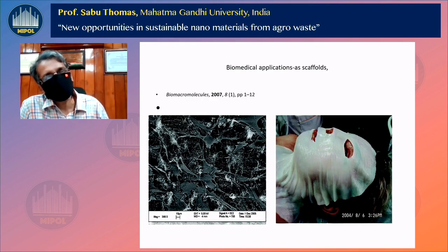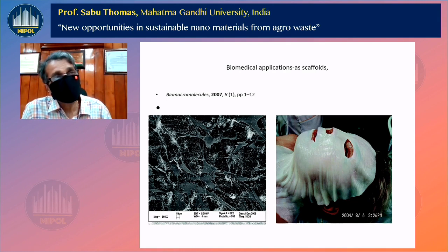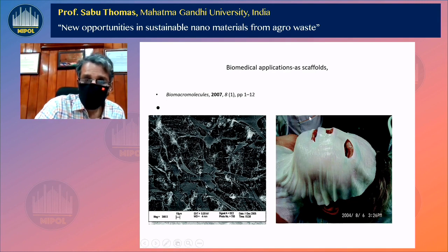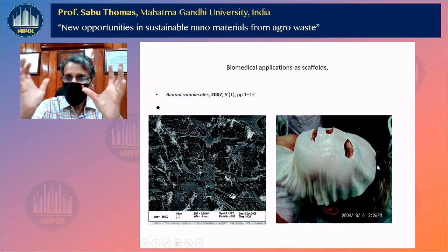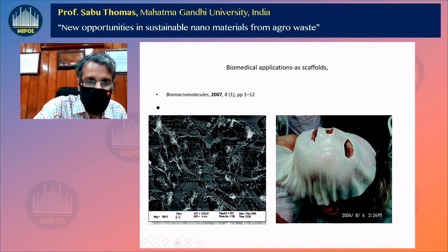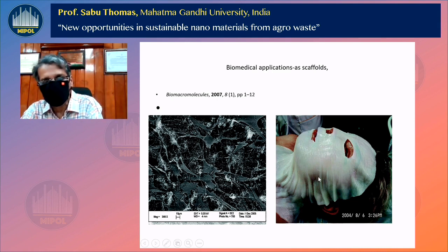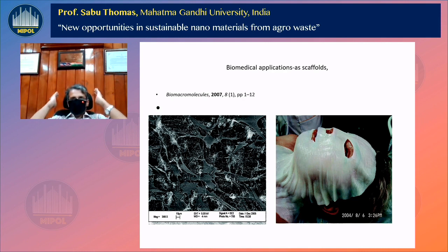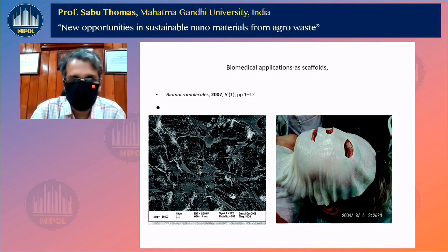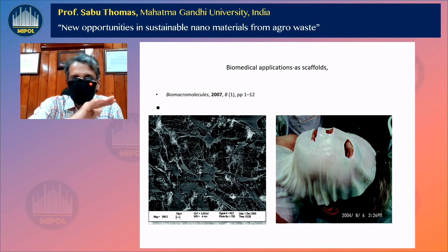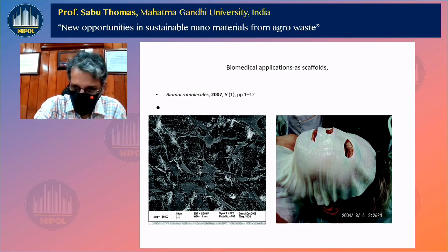Nanocellulose is a good platform for regeneration of cells. You can see a gentleman suffering from a high degree of burns on his face, and his face is covered with a gel of nanocellulose. Nanocellulose is extremely porous. You can see from this microscopic picture. And when you apply this gel on the surface of the burned skin, regeneration of the cells is so rapid and so big. It is an excellent platform for burns, regeneration of cells.